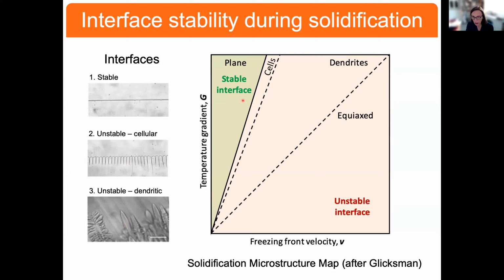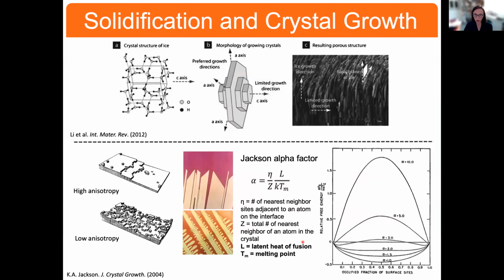So basically, if we can follow this map, if we have control over freezing front velocity and temperature gradient, we can move microstructurally through this map. If you go too far, you just get an equiax structure. So that's one important feature of all of this, that these parameters are at your disposal to then control the shapes, the morphology of these pores.